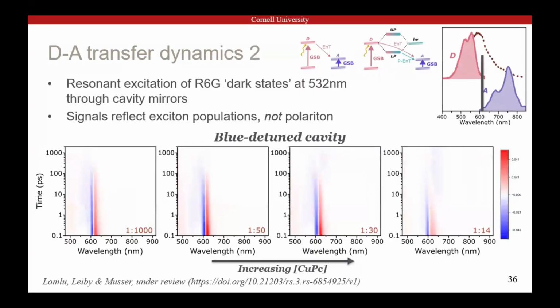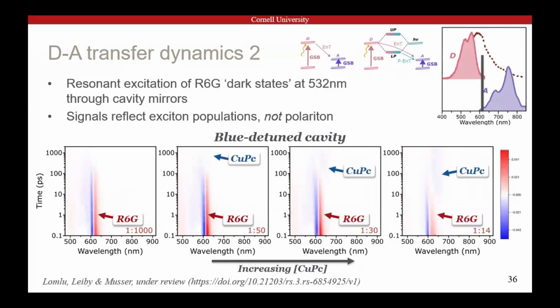But this is just because of weird optical effects that happen when you photoexcite a cavity. These are well known as artifacts, but we can read them because the nature of the artifact depends on where the photoexcitation sits. It looks like this derivative when the excitation sits on rhodamine, and the derivative actually flips over when it goes onto the copper phthalocyanine. So again, we can map this as donor transfer to acceptor.